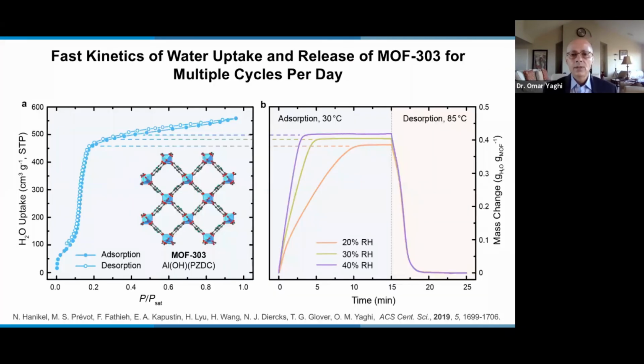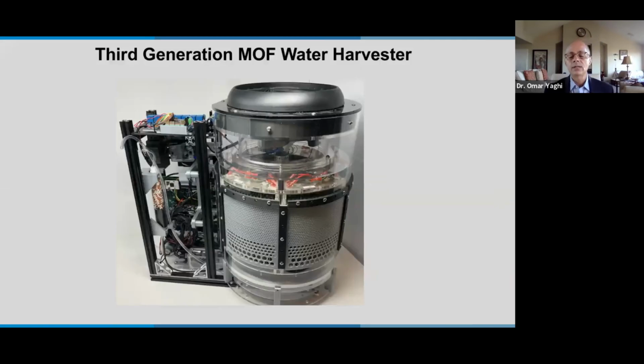So the reason these results are very, very exciting is because this MOF not only takes up water at low humidity, but it releases the water within minutes. And you can heat it up to 50 degrees or all the way up to 85 degrees to control the kinetics. But even at these mild temperatures, you can see that in less than 3 minutes, we can release all the water. And that meant that under the right conditions, one can design a prototype that can cycle water for many, many cycles, hundreds of cycles a day.